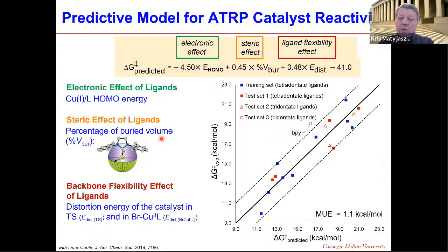But equally important for kinetics is flexibility of the ligand. It must go from copper-1 to copper-2 process, and in that case, sometimes can go from tetrahedral to trigonal bipyramidal structure. So ligands which are tetradentate, like TPMA or TREN, are really preferred because you have very little reorganization during this process.